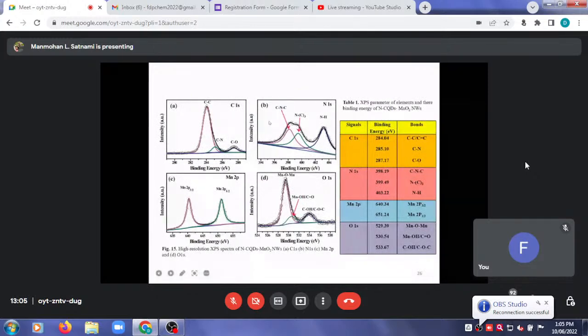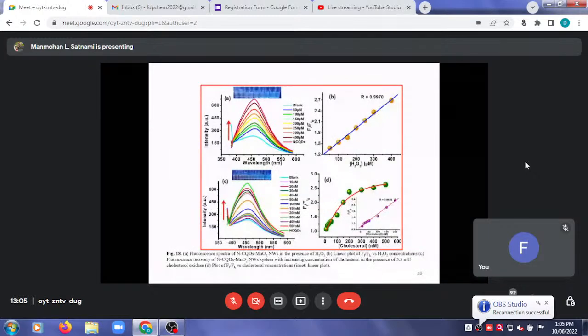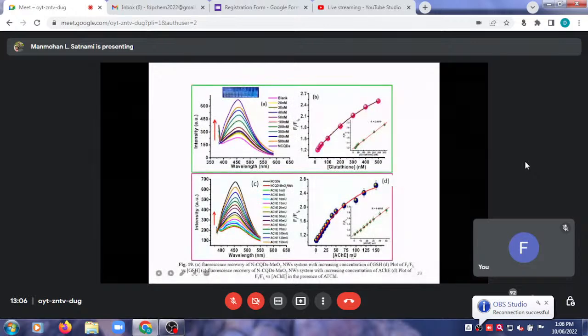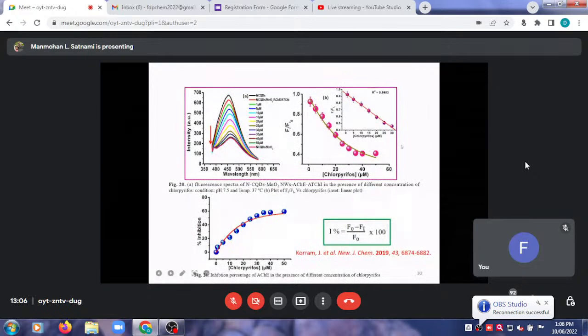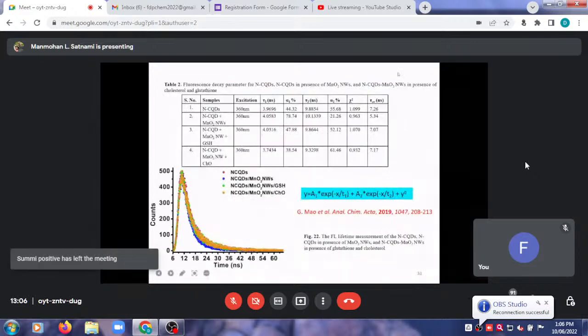This is the XPS spectra, and using this XPS spectra, we characterized that the carbon quantum dot is actually adhered on the surface of MnO2 nanowire, so that the FRET process can happen. From this linear regression curve, we calculated the limit of detection of hydrogen peroxide, cholesterol, glutathione, acetylcholinesterase, etc. And using these, we calculated the LOD of chlorpyrifos. This is different information regarding the fluorescence lifetime of the bare carbon quantum dot, and in the presence of MnO2 nanowires.